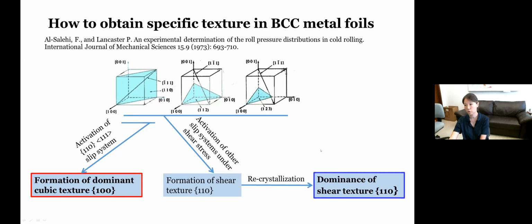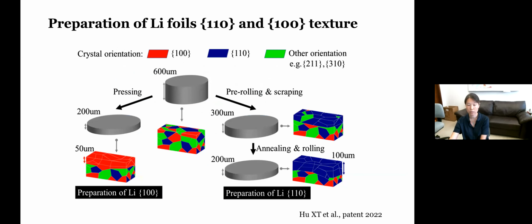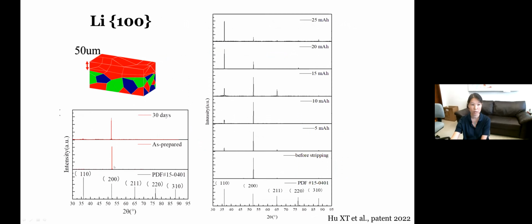Though in the earlier literature there are no experimental protocols, so we took a bit of time to see whether we can work it out. We took a pristine lithium foil that is commercially available. And the first trial is quite straightforward. We know by applying certain stress to the system, we would be able to activate the 110, 111 slip system, and that will give you the cubic texture. So we did. By using a hydraulic press at a pressure of 5 megapascal, we were able to generate this very nice 100 texturing of the lithium, as shown here.